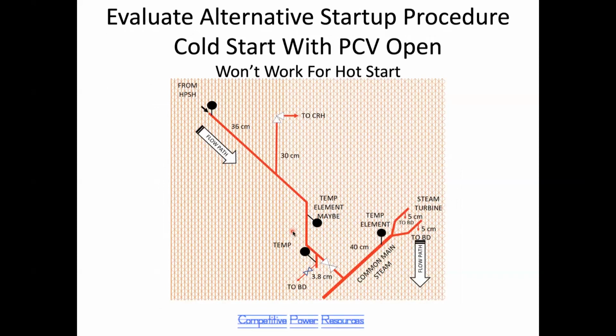There have been some attempts, successful in some cases, to solve this problem, and that's to start the unit with the bypass fully open. So that's what I've drawn here. Bypass is 100% open. This is a cold start. We can get away with that on a cold start because there's no pressure in the boiler to pass through the bypass until we generate some. So again, it's a cold start. Our isolation valve is open. Our flow path is as it was before, down to the turbine and through the bypass.